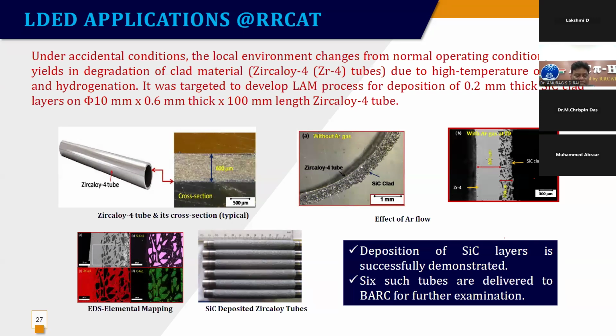So the idea is, can we have silicon carbide deposited on a zircaloy 4 tube? You have to appreciate that the thickness of the zircaloy tube here is 0.6 millimeter, and the silicon carbide of 0.2 millimeter has to be deposited on it. We started working on it. A lot of issues were there. There was burning of the tube, fusing, many things happened. And even the dilution was very high.